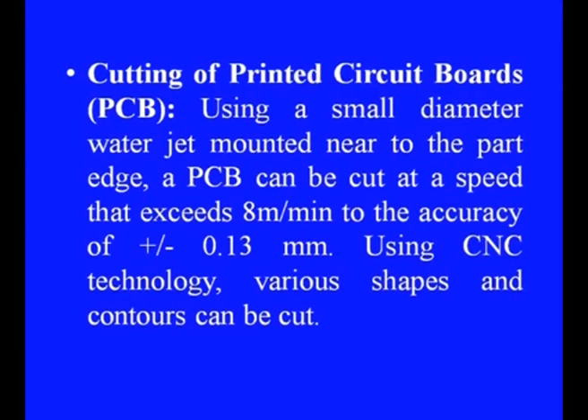Another application is cutting of PCBs or printed circuit boards. Using a small diameter water jet mounted near the part edge, a PCB can be cut at a speed that exceeds 8 meter per minute to an accuracy of plus minus 0.13 millimeter. Also, using CNC technology, various shapes or contours can be cut. This process can also be used for surface treatment like removing deposits and residues without any toxic chemicals, which eliminates costly cleaning and disposal problems.